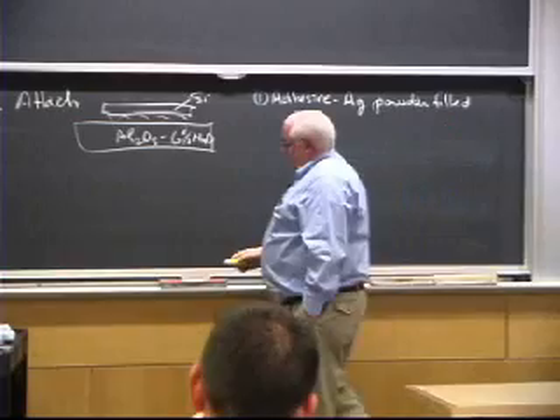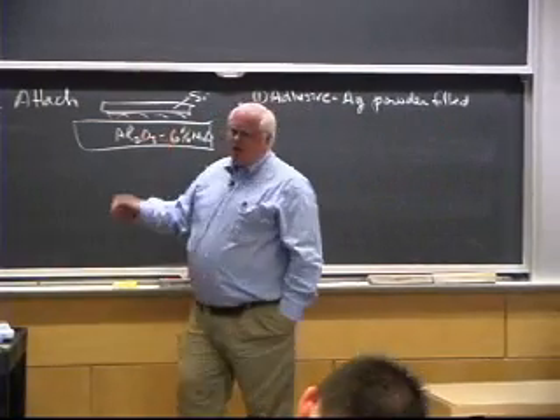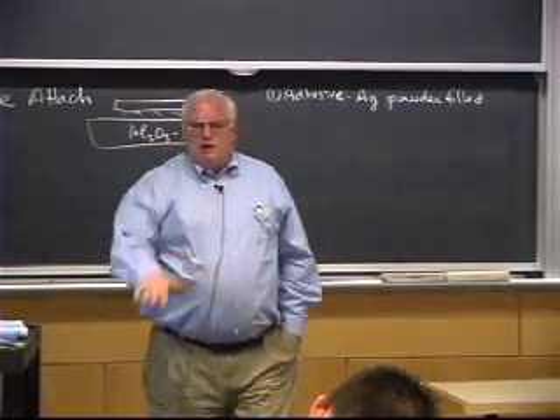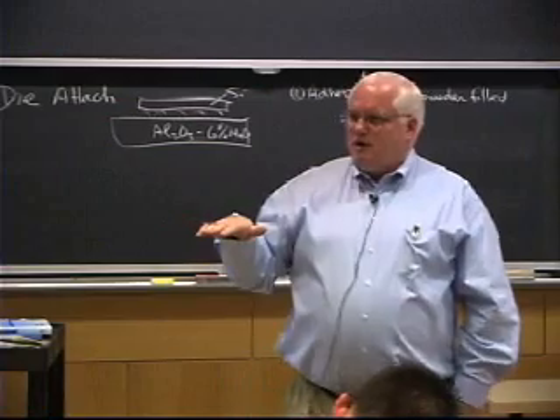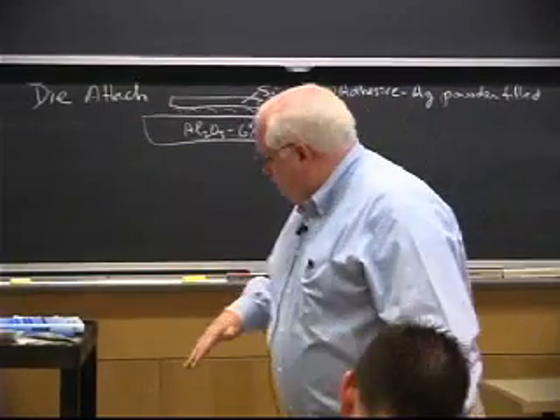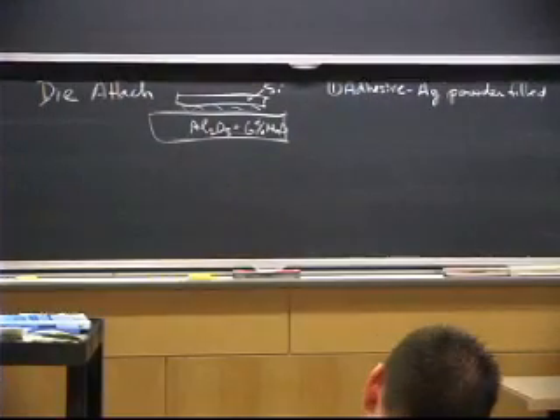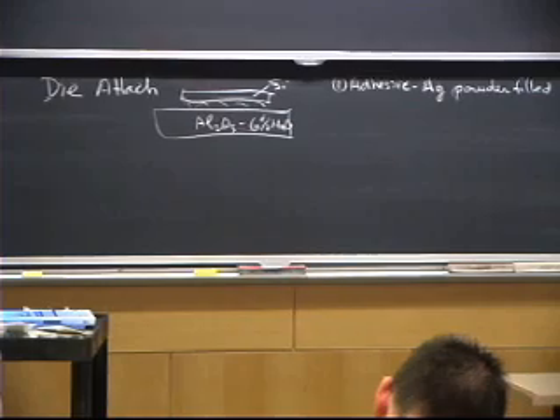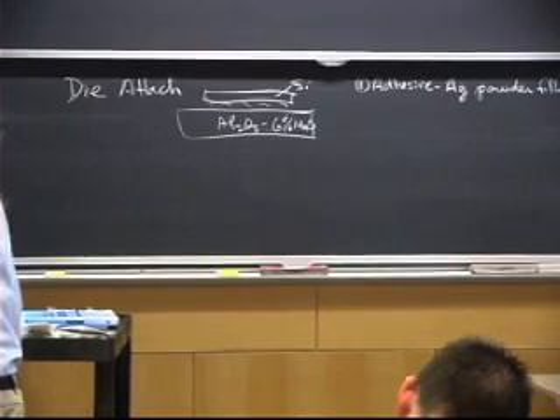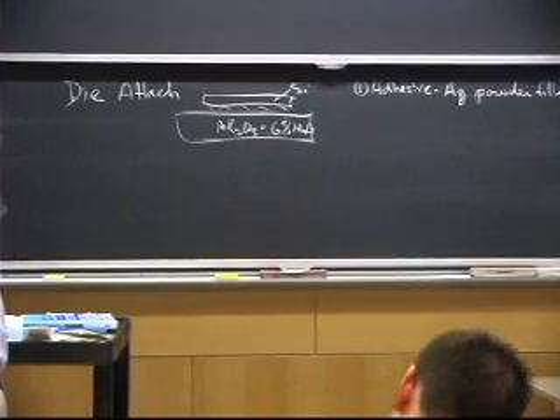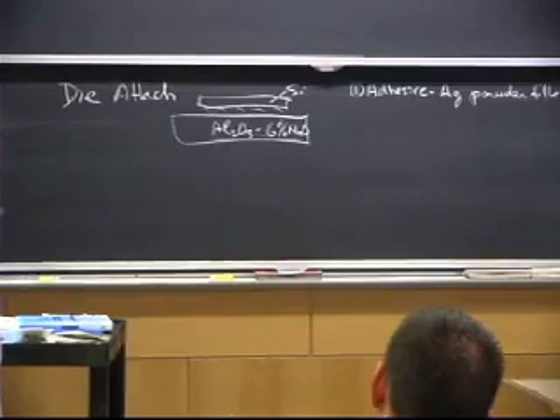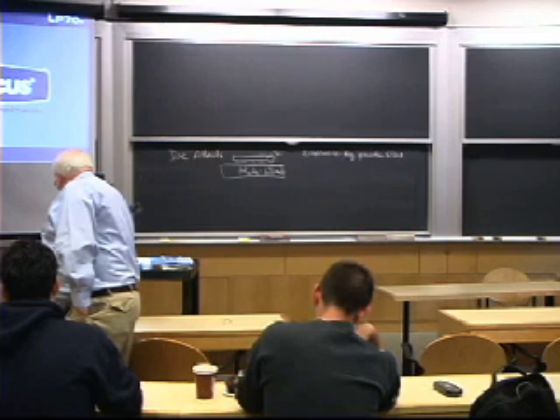These things operate, I mean, we're now at 2 and 3 gigahertz and pushing towards 4 gigahertz. These things need a ground plane on the backside, or they run into all kinds of problems. So they typically use an adhesive that has a silver powder in it, and the silver powder gives good thermal conductivity. It also provides a ground plane to the metal to the substrate.